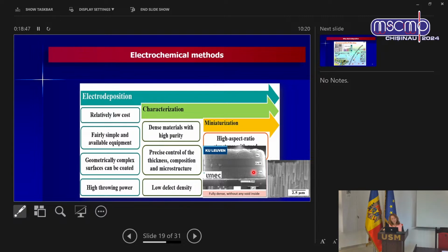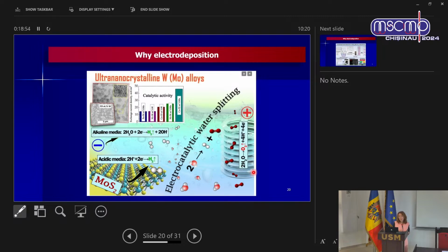And here also briefly, without entering into details, if you are interested, you can find them in publications. Here I just represent that, for example, we were able to achieve coatings with refractory metals like tungsten, molybdenum, and we are calling them for the first time ultra nanocrystalline alloys. Because the crystalline size detected by XRD is very, very small, like 5 nanometers, 4 nanometers, which is really already tricky. And when we published it in Electrochimica Acta, of course, we made also TEM to show that you cannot practically distinguish anything. So instead of calling it amorphous, we call it ultra nanocrystalline.